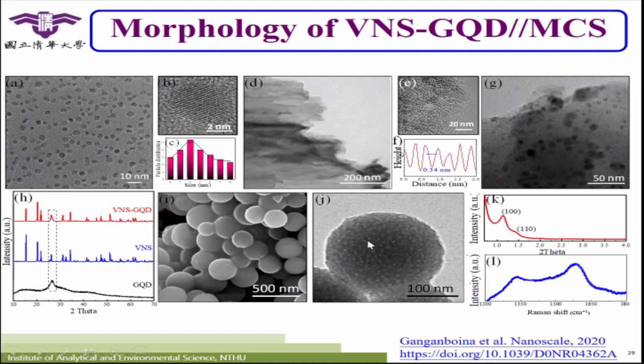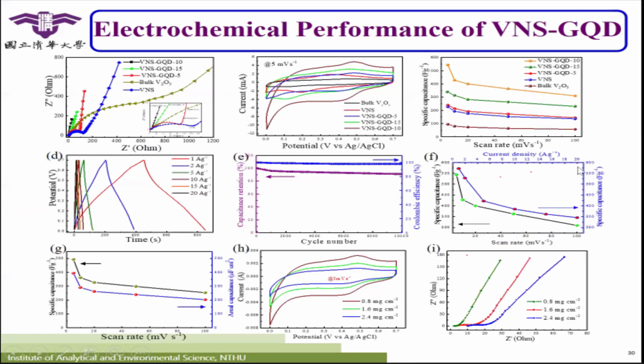And then from the TEM, we can see they have some nice spots here. This one is their pore here. So here we can see the low angle XRD, and they are quite good. And from the Raman spectroscopy, we also can see the D and G band here. So we use these two together and their electrode property will be good.